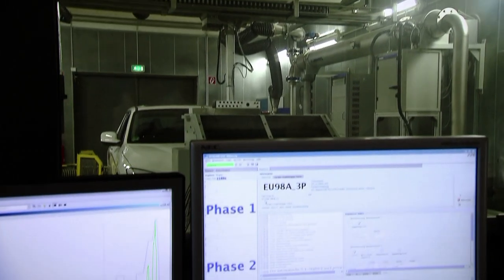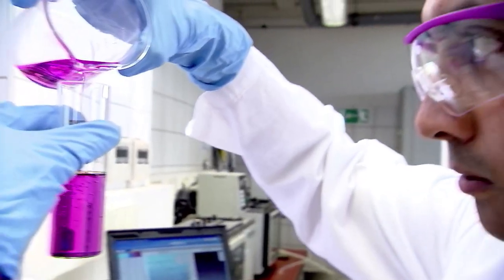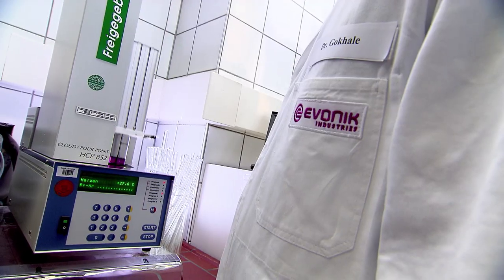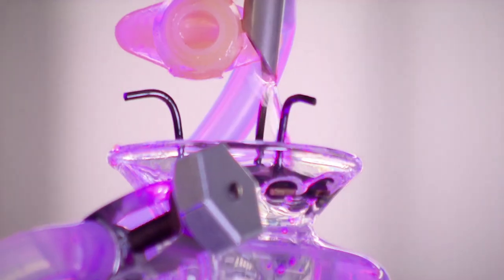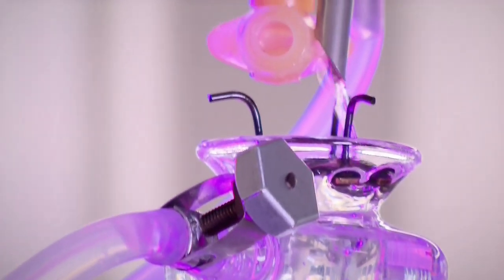Testing in the performance test lab and chassis dynamometer provided validation. The comb's exceptional performance as VI improvers pushes the well-known mechanism of polymer coil expansion and collapse to the extreme. Combs deliver significantly greater increases in viscosity index and oil thickening for the same shear stability performance of a regular PAMA or commodity polyolefin. They far exceed the performance of known incumbent chemistries, and in addition give formulators no cause for concern on cold flow behavior, typified by performance in Brookfield or MRV TP1 tests.